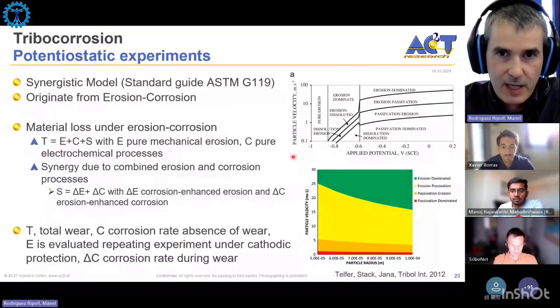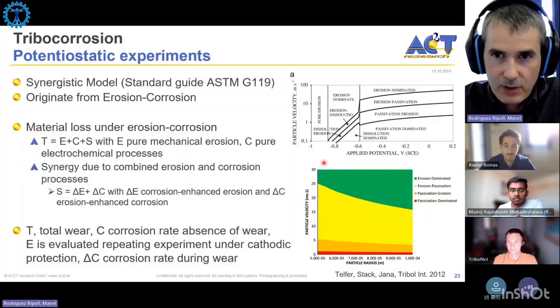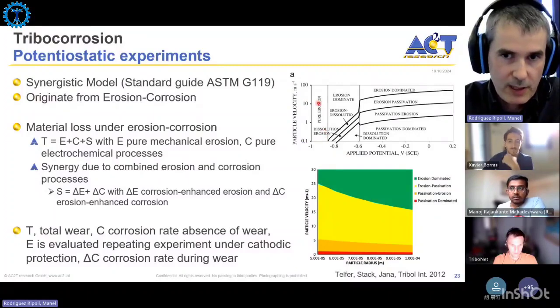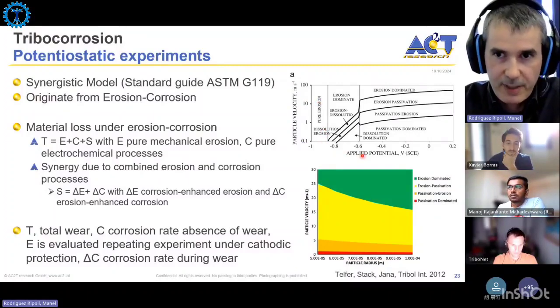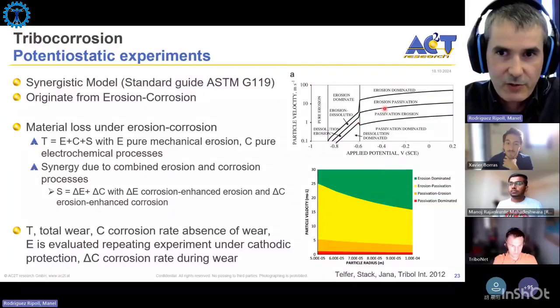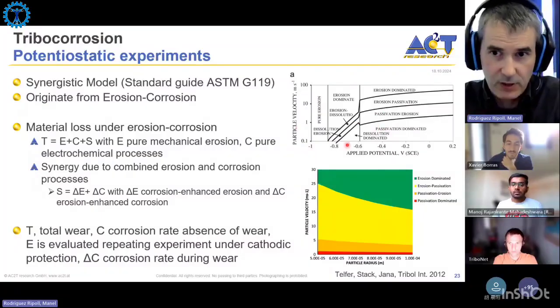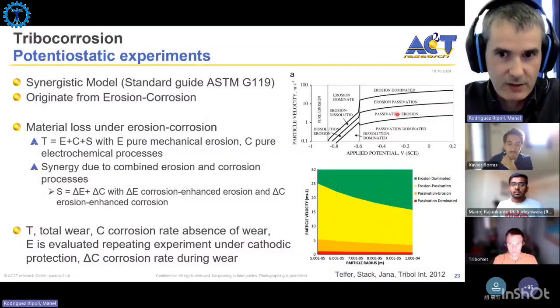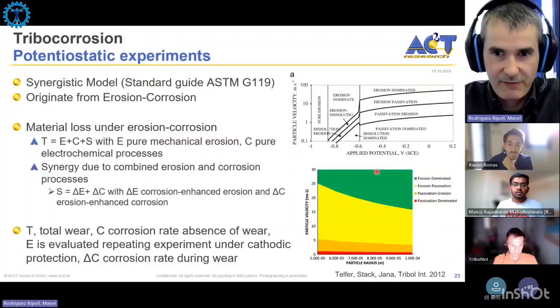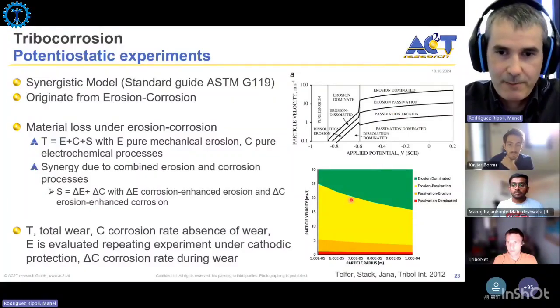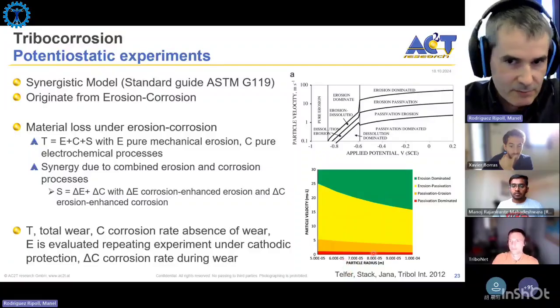So, for example, you have the particle velocity in erosion processes as a function of the applied potential, and you can see, for example, that for cathodic potentials, you can have here pure erosion because you are under cathodic protection. You can have places where erosion dominates at very high impingement velocities. Other places where, for example, if the particle velocity is very small, then you are dominated by corrosion, and you also have intermediate states. Or you can also make different maps where you plot the particle velocity as a function of the particle radius, for example, if you have different types of abrasives, and you can get all these kinds of different maps.